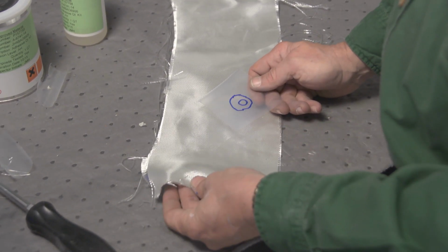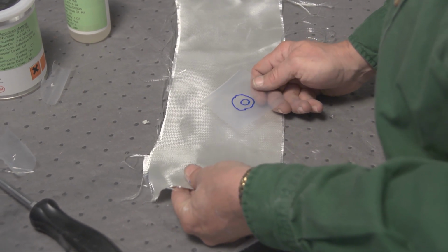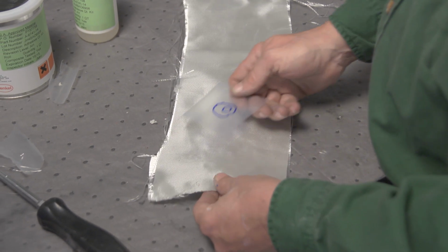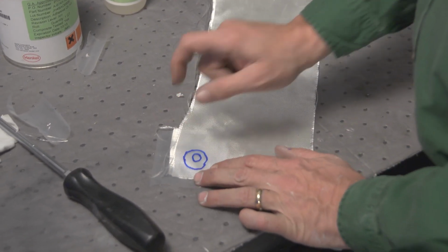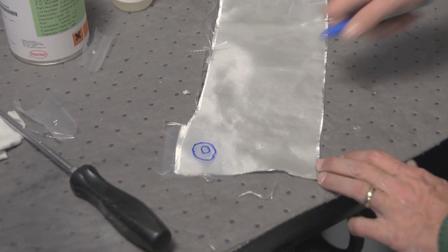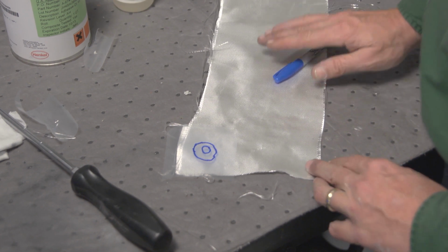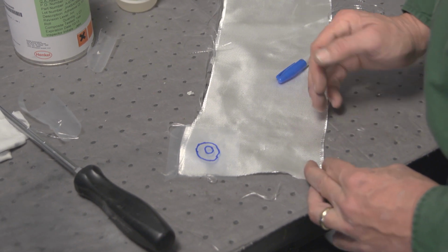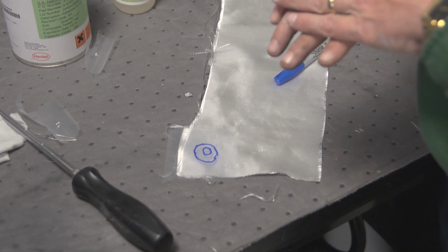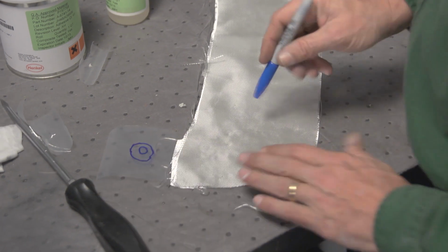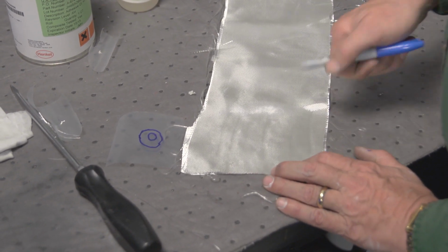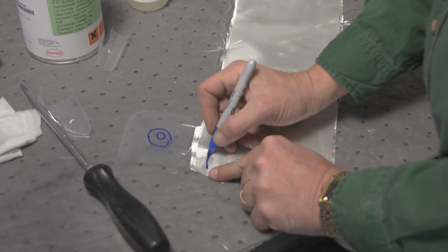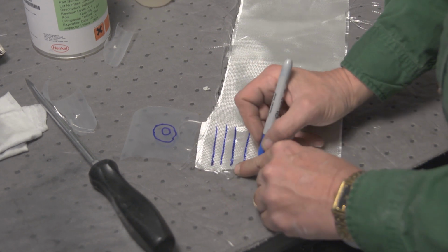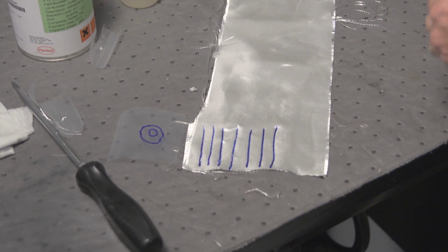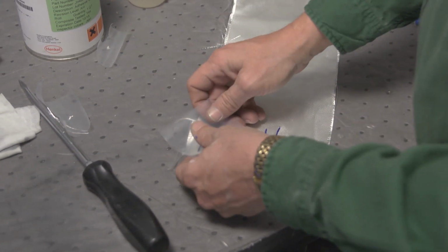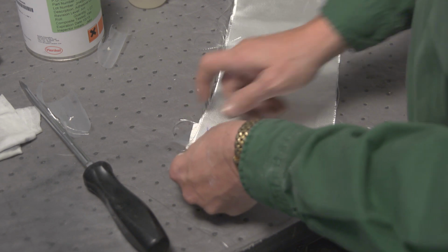This is e-glass, and it's used to repair the N7605 blade, the carbon Kevlar hybrid blade. Before I cut this template out, the weave of the fabric is important. You want to have your material, when you apply the second piece, at about a 45-degree angle to the previously cut piece. So the easiest way to do this, because this material weave is so fine, I just make some parallel lines with a marker. And then I'll put my template on, and I'll cut out my first piece.